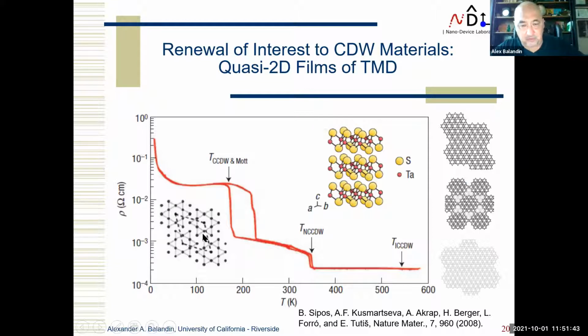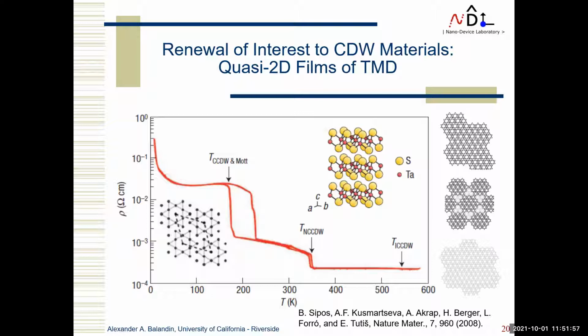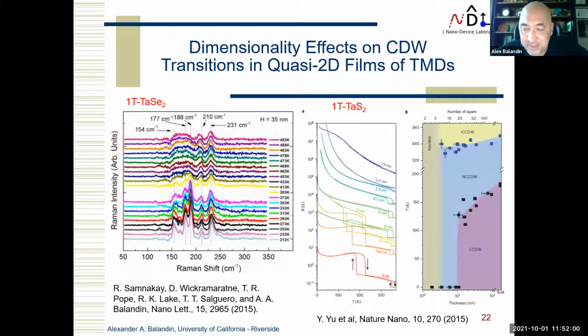I just love this picture because it puts it very nicely. Indeed, this hysteresis is much larger, as is the change in resistivity. However, I do want to have something which works at room temperature. That's my first motivation. And the second one, I also explained to you: if I want to go to nano, any device now has to have nanoscale dimensions, and this large hysteresis at low temperature actually disappears. This is work from other people. We also achieved the same results, so it's completely proven.